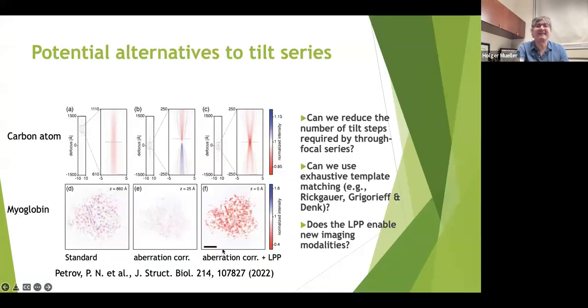And finally, as a last slide, if I have dual phase plates whose phase shift can be varied at will, that offers new imaging modalities that we're studying together with our postdoc, Peter Petrov. Here you see some simulations of the point spread function for that as applied to imaging a carbon atom. And this is standard mode. This is with aberration correction. You can see the higher numerical aperture leads to sharper features. And this is with phase contrast. And you see this very sharp feature at the center of the point spread function. And this leads to simulated images of myoglobin. So we hope that soon the CZI microscope will allow us to study this.